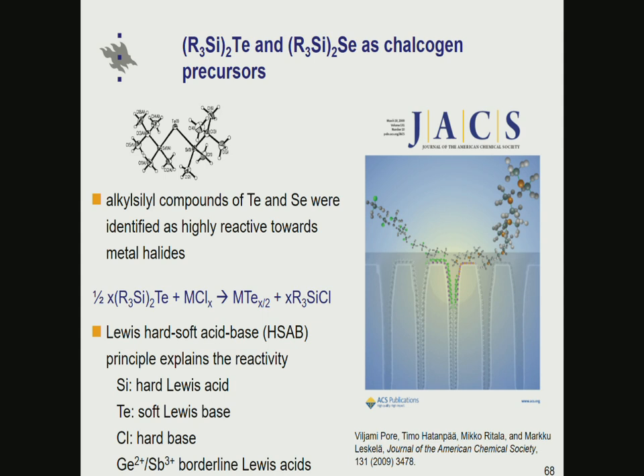This is again a story from our group. Our collaborating company requested us to develop chemistry for depositing germanium antimony telluride compounds by ALD, because these are potential phase change memory materials. At that point we knew that these three elements had been poorly studied in ALD, and what had been learned so far was that they are difficult in ALD. We were quite skeptical about our possibilities to develop this kind of chemistry, but then we came up with the idea to use this alkyl silyl.